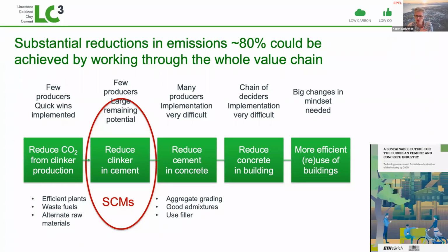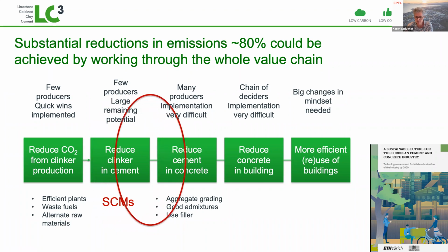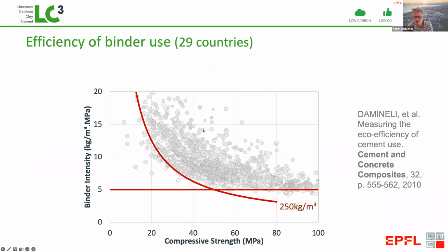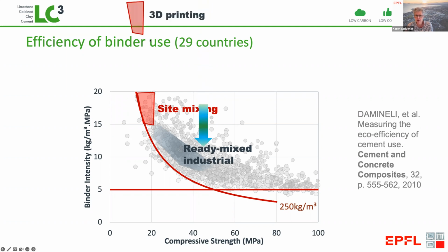Before finishing, I just want to say that this is only one part of the chain. If we worked at all levels of more efficient clinker production, less clinker in cement, less cement in concrete, less concrete in buildings, we could potentially save about 80% of the emissions. Just looking at the cement in concrete, we see today there's tremendous dispersion, tremendous wastage. One way this can be reduced is by going from site mixing to ready mix. However, what we do not want to do is start concentrating on 3D printing, because this is a very inefficient way of making concrete, exactly the reverse of what we need to confront climate change.